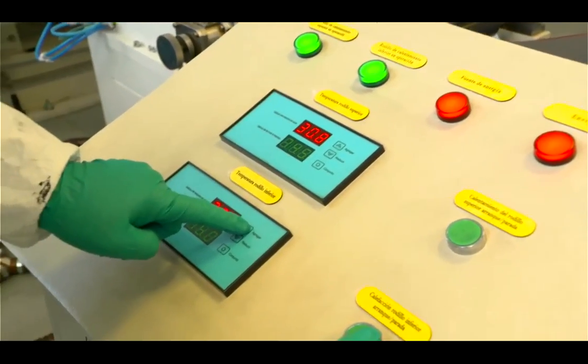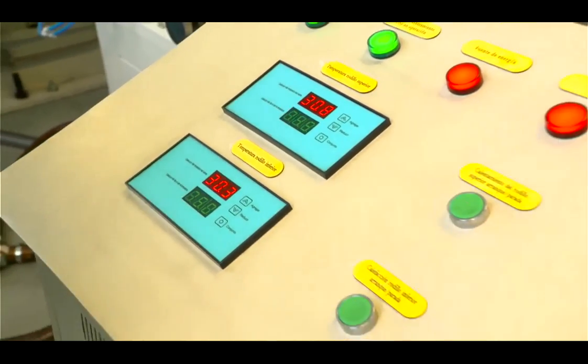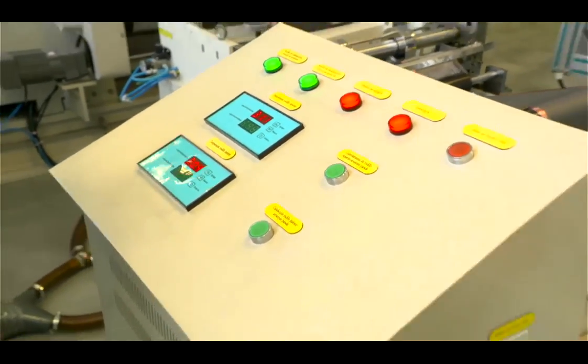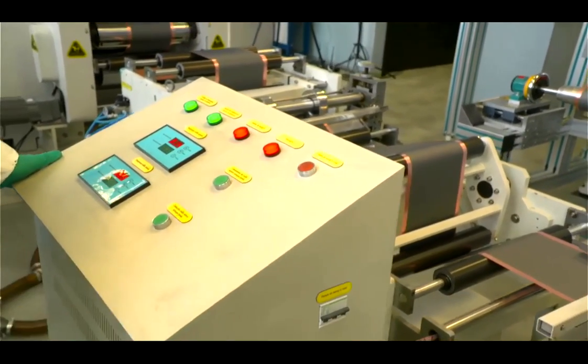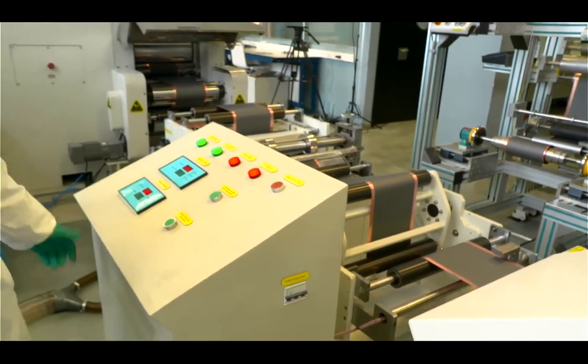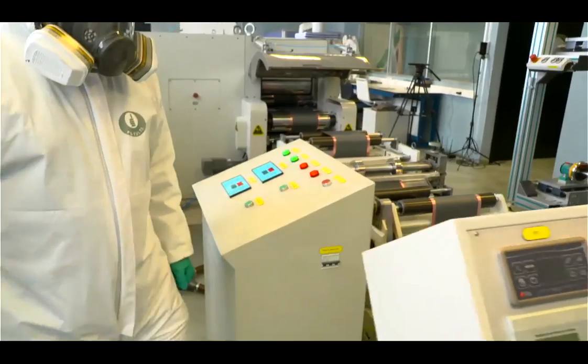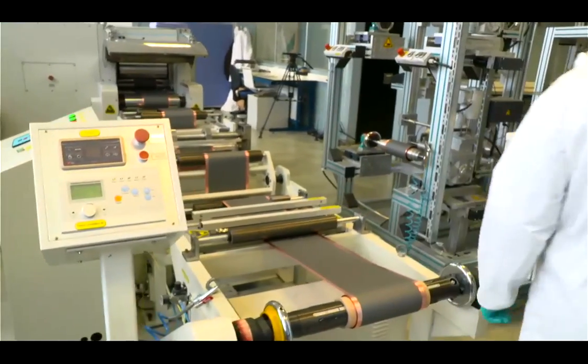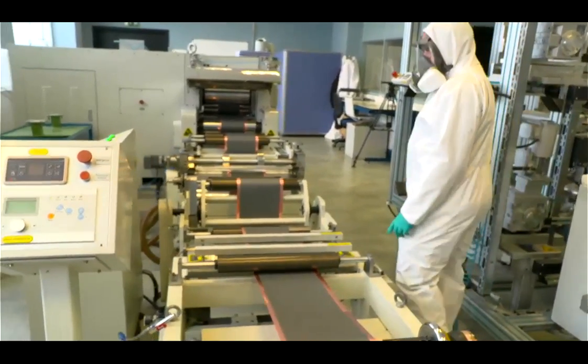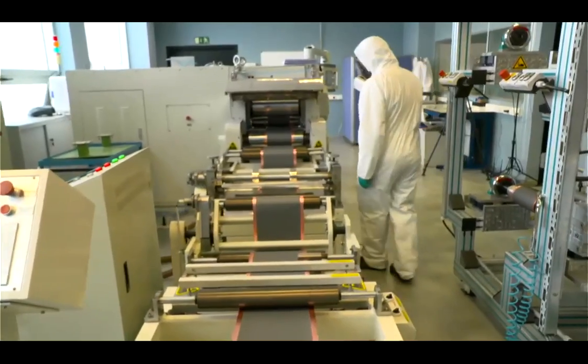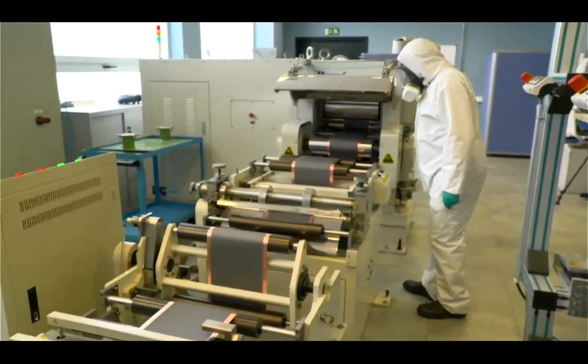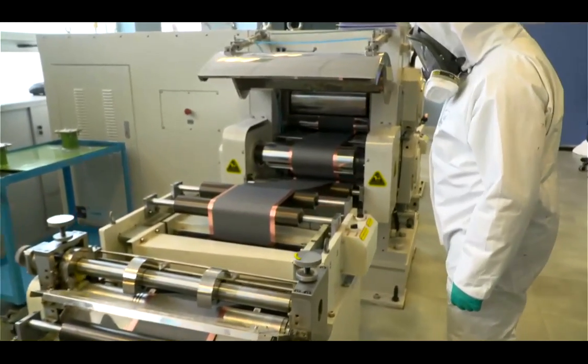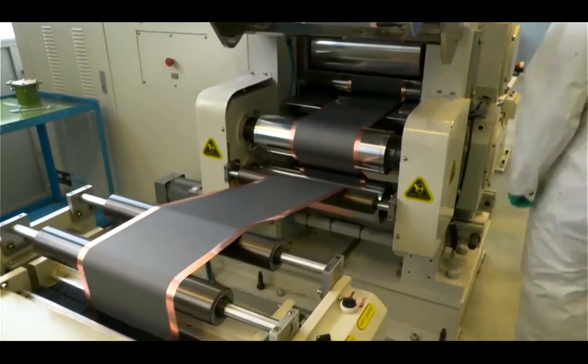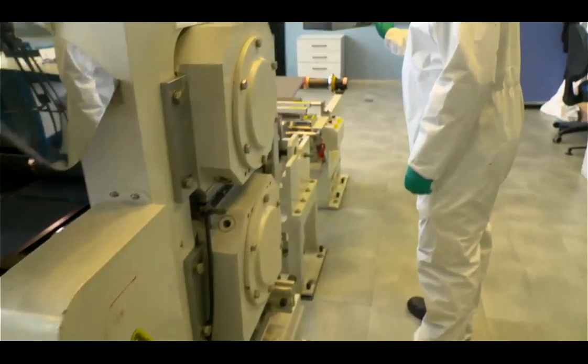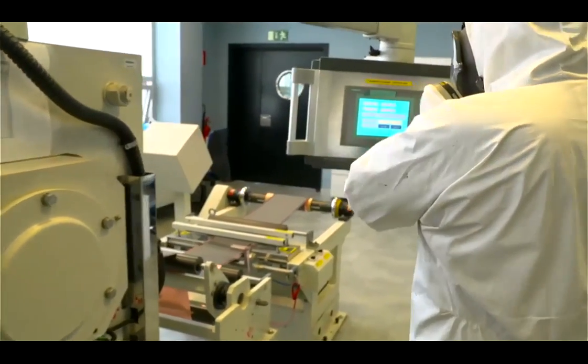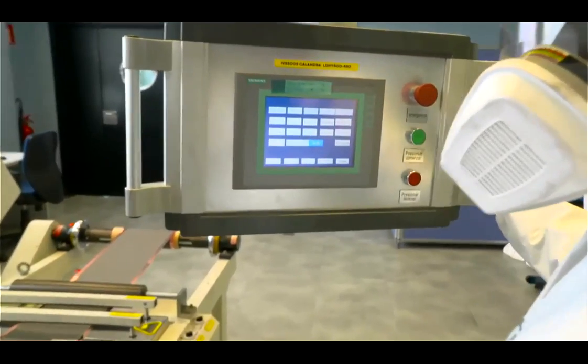Yeah, it's true that we are trying to avoid it, but sometimes depending on the binder that we are working with, it requires this heating in order to activate the binder. So everything depends on the formulation. Actually, sometimes there are some PVDFs that require going above some Tg to melt and to make this binder effect. So if we are working with this special PVDF, for sure then we are forced to do that. But with a standard formulation, I would say it's not necessary to warm up or heat up the rolls.